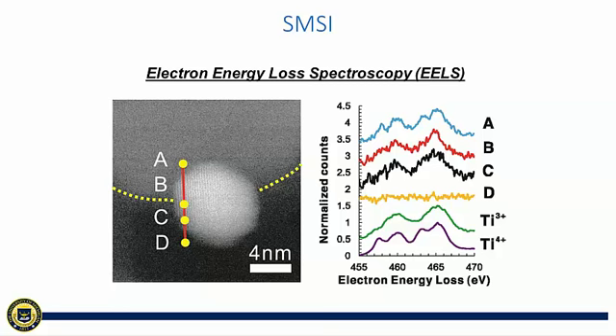I also did an EELS line scan of the sample at 500 C under forming gas. Here we can see the valence of titanium is 4+ on the support and changed to 3+ on the metal particle, indicating the support has now been reduced by forming gas, but the particle is covered by a very thin layer of reduced titanium.